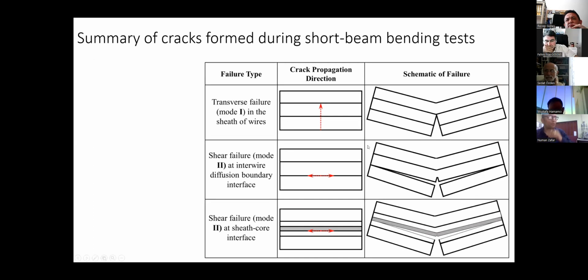So this is the summary of the cracks. Shear longitudinal cracks are formed at interwire boundaries and sheath core interfaces, and we expect that from a material like this. And the transverse cracks are formed in the core, and if a transverse crack is formed in the wire, and as I have proved, the transverse cracks formed in the wires propagate to the next wire, you see a mode 1 failure, an immediate failure.